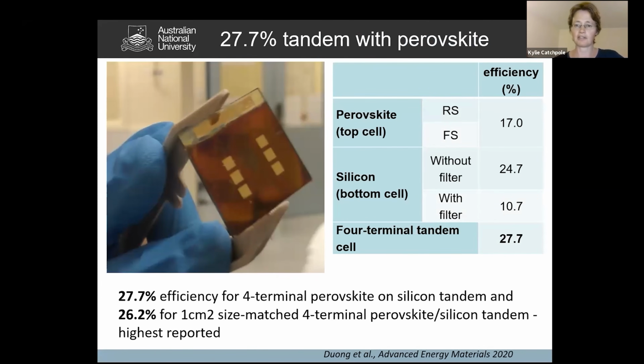So in this kind of configuration, we were able to combine a perovskite top cell with a silicon bottom cell. This perovskite top cell by itself had an efficiency of 17% for the semi-transparent cell. Combined with a silicon bottom cell, we're able to get an efficiency overall of 27.7%. And when we did that for a size matched case, that was 26.2% for a 1 centimeter square size matched 4-terminal perovskite silicon tandem.